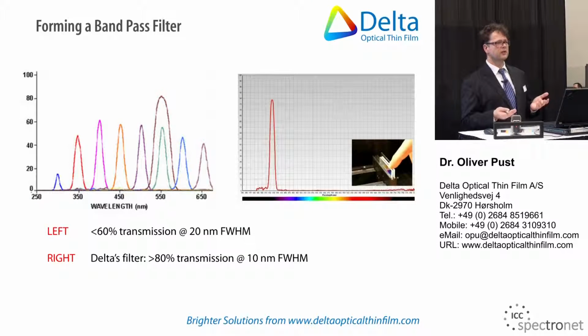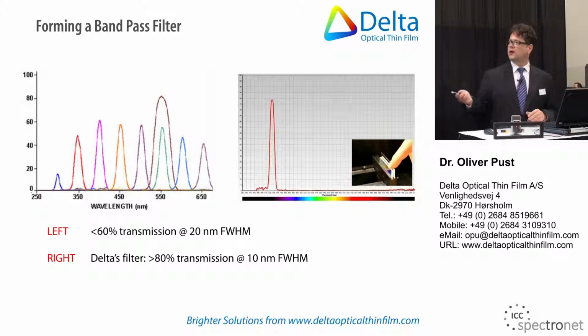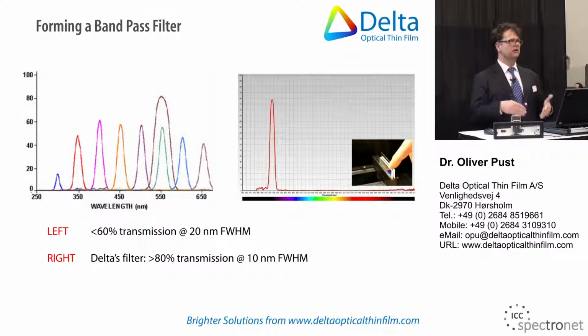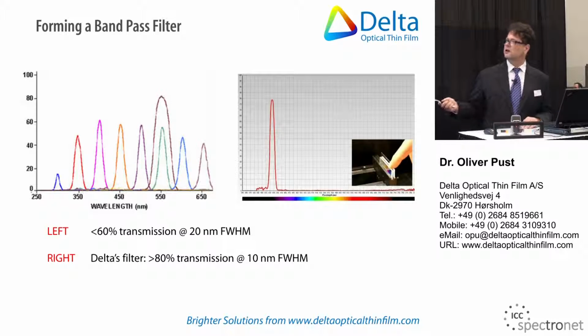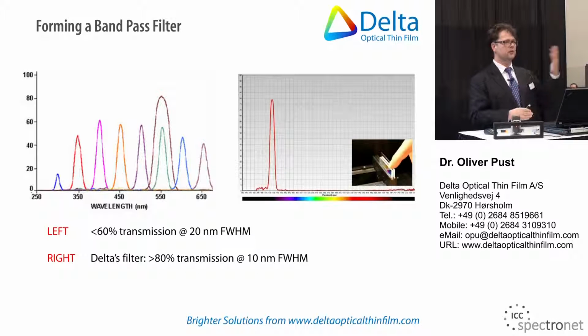And again, the comparison with older technology. On the left-hand side, you see if you want to make a band of 20 nanometer, your transmission already drops to about 50–60%. And if you make it even more narrow, you get even less transmission because of the very sloppy edges. If you want to have at least 80%, you need to make a 40 nanometer wide band. And as you recall, with our solution, you can make 10 nanometer bands at full maximum transmission, about 90%.